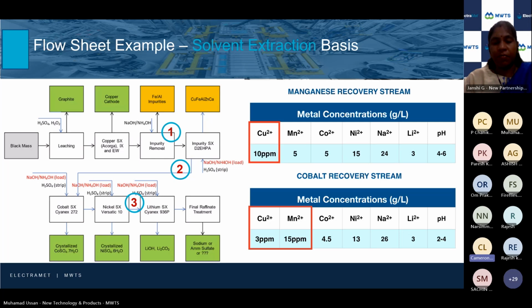The solvent extraction and the chemical precipitations are not hitting purity requirements, which is going to be 1 to 2 ppm max on these product streams. And if you look here, right after step 1, that impurity SX, the D2EHPA, call it DEHPA, is usually very good at bringing out bulk manganese. And it's good at bringing out trace metals, but it's still not good enough, right? It gets 95% of the impurities out, but you need 99.99% of those impurities out.